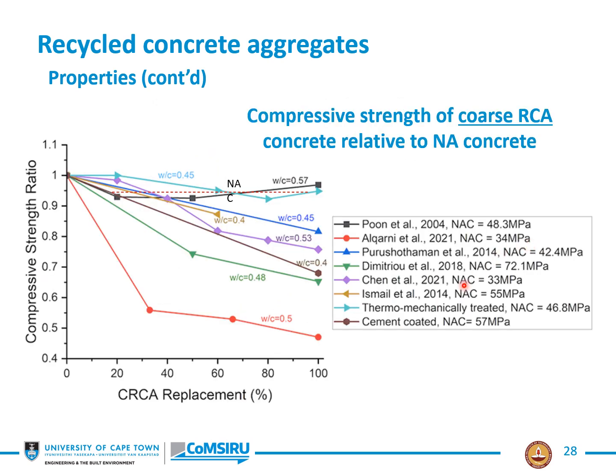Now, structural engineers are always interested and concerned about compressive strength. So what does that mean? Well, here you can see, again, a high variability of results from a series of references. But the important thing to note is that in many cases, or certainly in some cases, it's possible to get very little reduction in compressive strength of the final concrete, even at 100%, and this is coarse recycled aggregate replacement. On the other hand, you can see this plot here, or even some of these, there can be a very substantial effect on compressive strength, which is obviously what we don't particularly want.